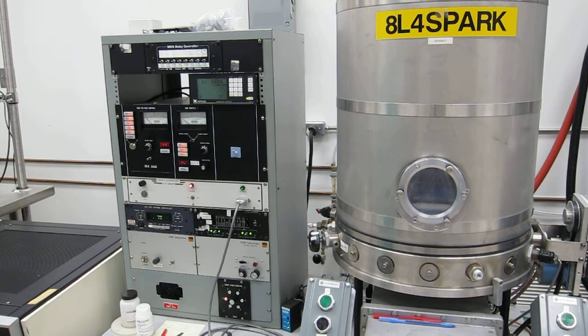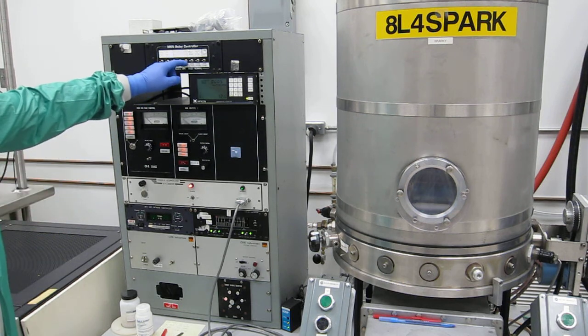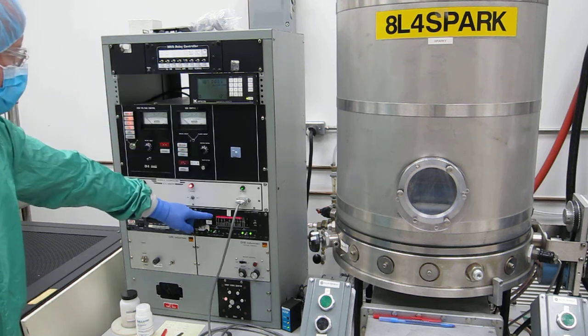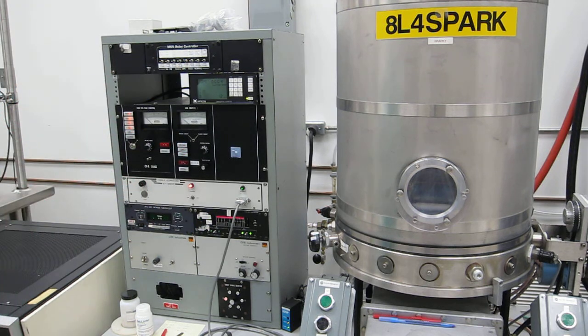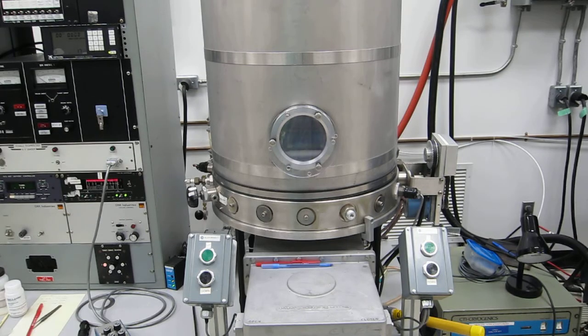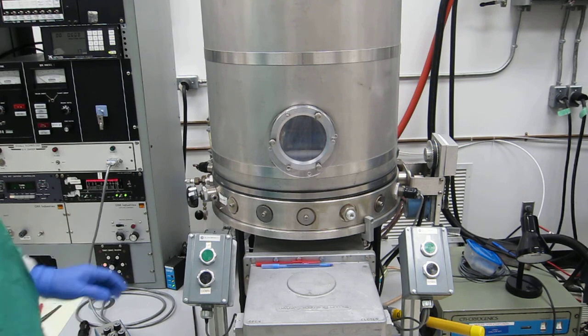Finally, we have to vent the chamber to atmosphere. We do this with dry nitrogen. Notice the chamber pressure coming back up. It'll take a few minutes. The chamber will now fill with dry nitrogen, and we'll be able to raise it to remove our substrates. With the chamber venting complete, we can now raise the chamber to remove our substrates.